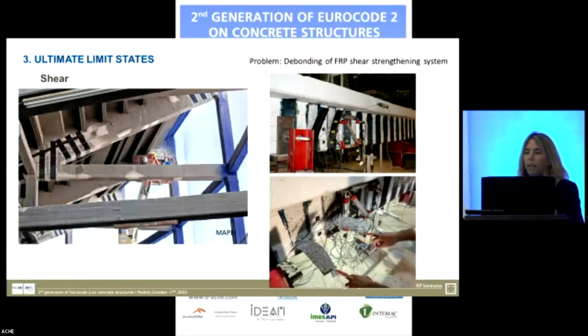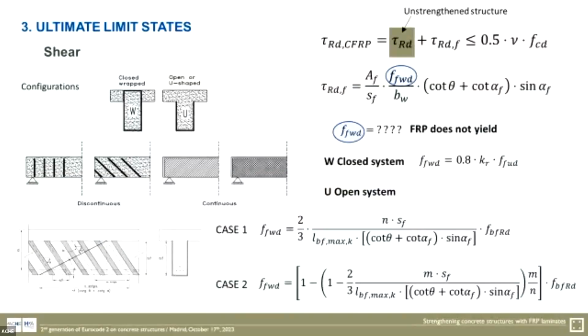But the main problem, again, might be the debonding of the FRP in certain configurations, especially in U-shaped configurations, the ones that are not completely wrapping the section. You can see debonding once the critical shear crack appears and propagates, as you can see in the pictures on the right-hand side. So we have two configurations allowed in this Annex J, the closed wrap, which is wrapping the transverse section, or the U-shape configuration. They might be continuous or discontinuous.